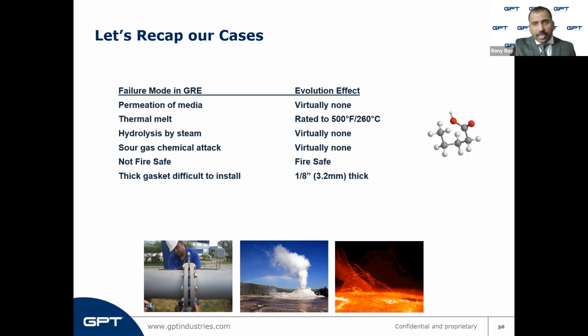In the second case, Evolution has a much higher operating temperature rating than either G10 or G11 and would have worked well in an application requiring exposure to higher temperature. The third case involving steam, Evolution resists hydrolysis by steam and would have survived that application too. The next case involves exposure to sour gas, and since Evolution is chemically compatible with the levels of sour gas that was present in this application, it would have performed well even in this application.